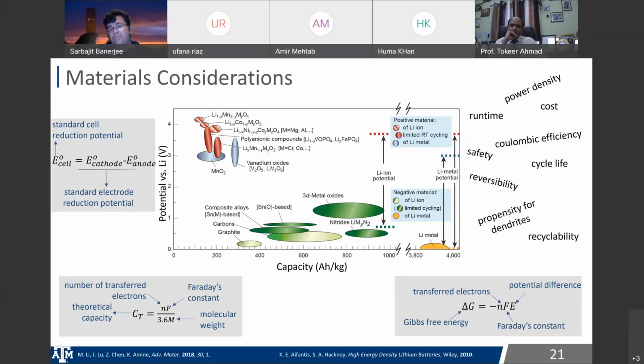So a big dream for the entire field, something a lot of folks are working on, is to be able to use lithium metal anodes safely, reliably, and at full scale in large batteries. And this is yet an unsolved problem. There's lots of claims in the industry. Many of those claims have been proven to be not entirely true. This is a huge problem. How do we go from graphite to lithium metal? So a lot of folks are working on trying to mitigate the propensity for dendrites, and moving away from graphite-based anodes to lithium metal anodes.